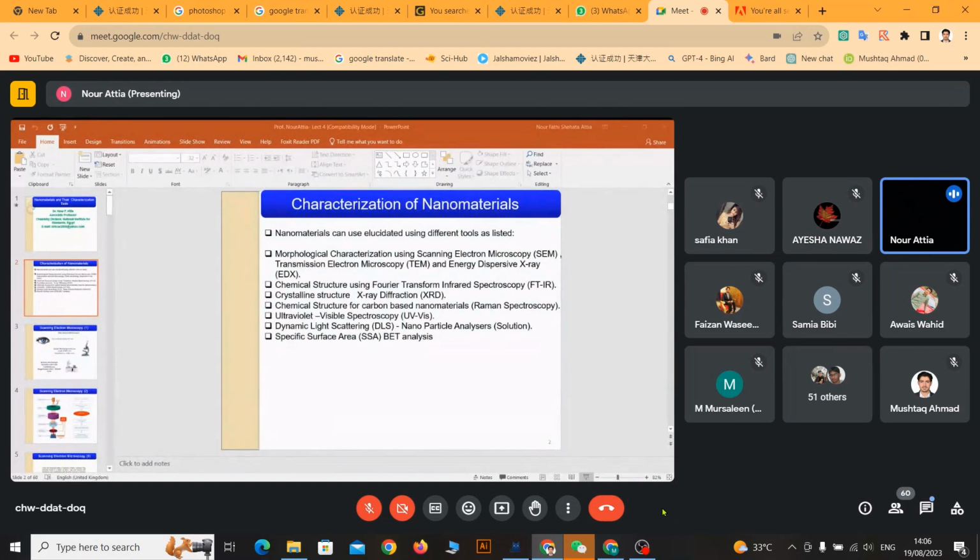at least 72 hours. So you have to measure using dynamic light scattering, because when you measure the TEM, you cannot see the hydration layer and the polymer surrounding the nanoparticle. You only see the nanoparticles, okay? And in this case, the nanoparticles could be like 30 or 20 nanometers. But when you see in DLS, it will be 50 or sometimes 80 or 100, because the laser will see the hydration layers, okay? Then finally, specific surface area for the nanoporous material.